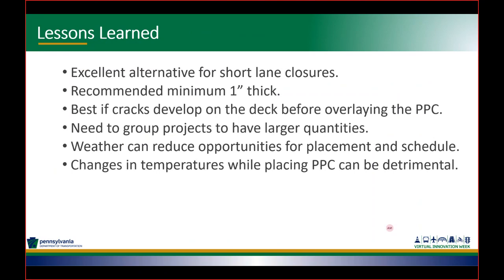So what we have learned from PPC, it's an excellent alternative for short lane closures. So you can open to traffic pretty quickly. You don't have to wait for material to cure. I mean, if you have a Schmidt hammer, I have seen overlays that they open at 1.5 hours after being placed. So it develops strength very quickly.